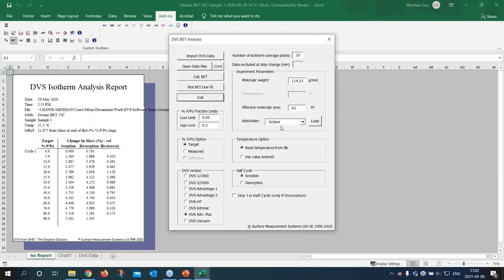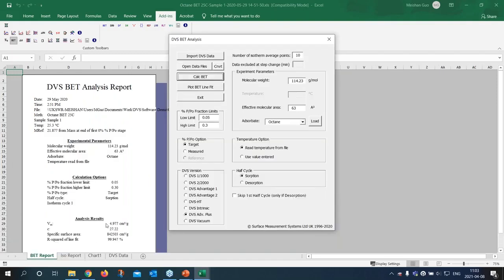And with this panel, it will automatically select the probe molecule you use for the determination. And it has already the parameters related to this probe molecule in the database. So basically, you don't need to select anything. You already have the BET range. Then you just press the button to calculate the BET surface area. It will generate a report with the monolayer volume, sorption constant, and the BET surface area about 842 square meter per gram.